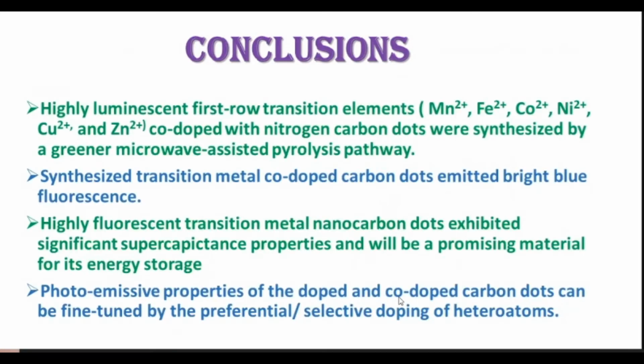So these are the conclusions that we can make from our work: highly luminescent first row transition elements manganese, iron, cobalt, nickel, copper, and zinc co-doped with nitrogen carbon dots were synthesized by a greener microwave-assisted pyrolysis pathway. The synthesized transition metal co-doped carbon dots emitted bright blue fluorescence, and these fluorescent transition metal nanocarbon dots exhibited supercapacitance properties, and thus they will be a promising material for energy storage.